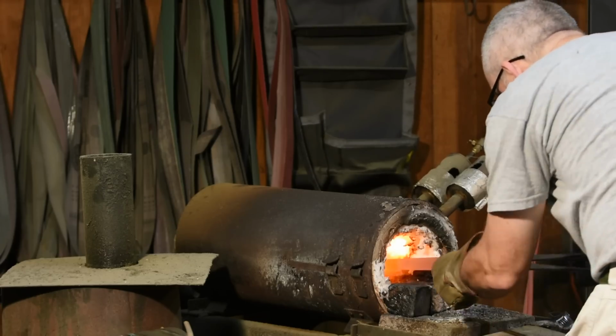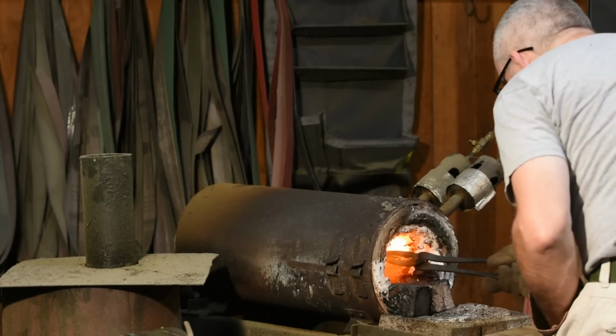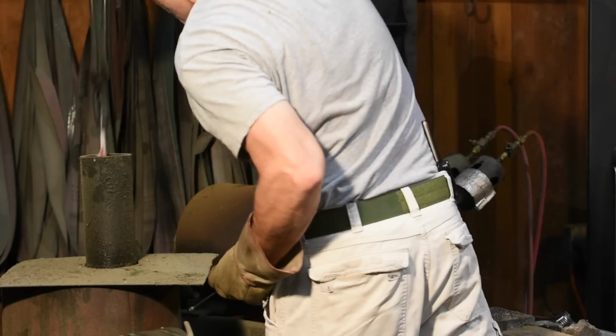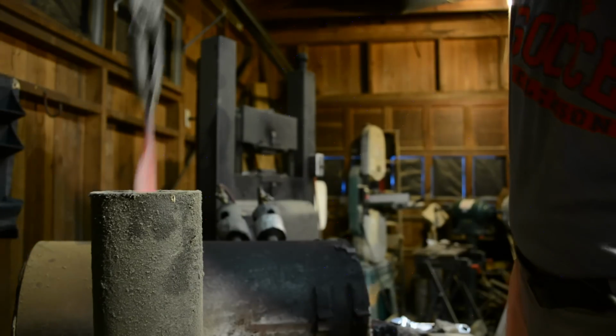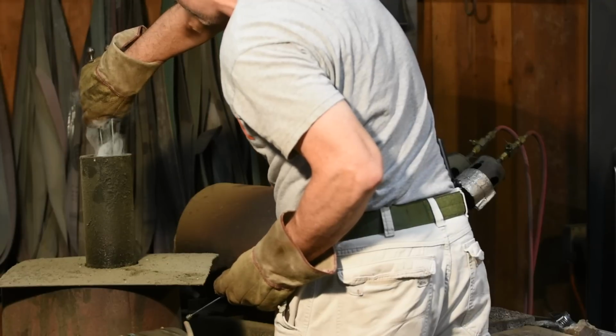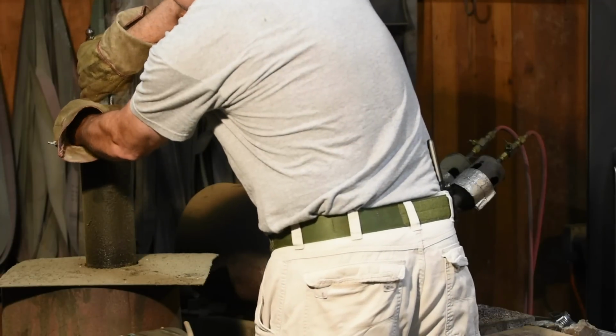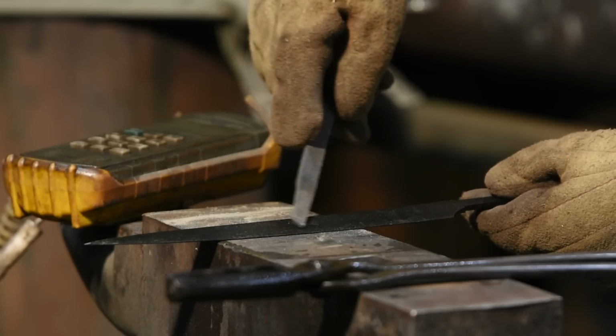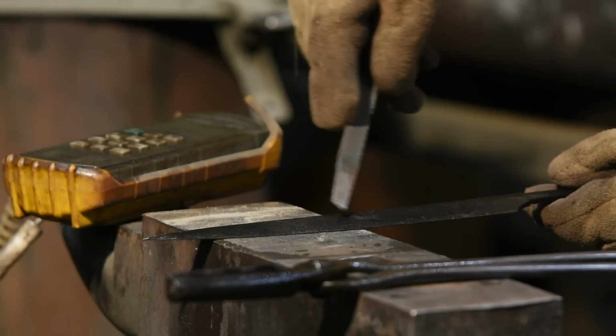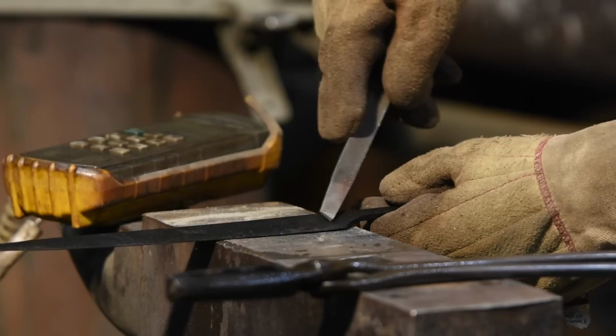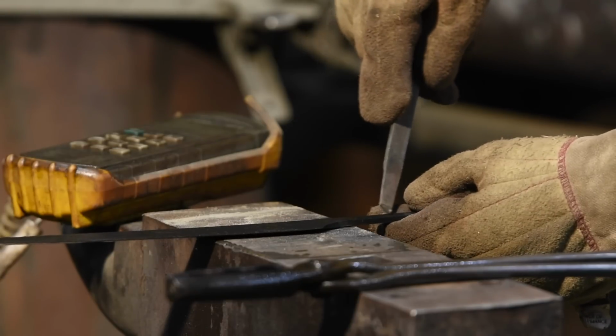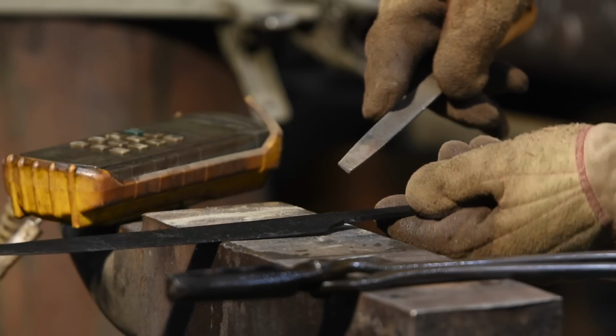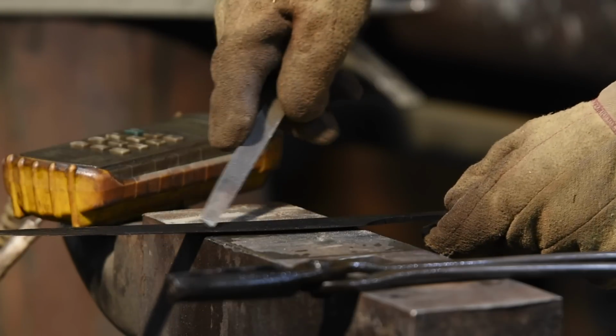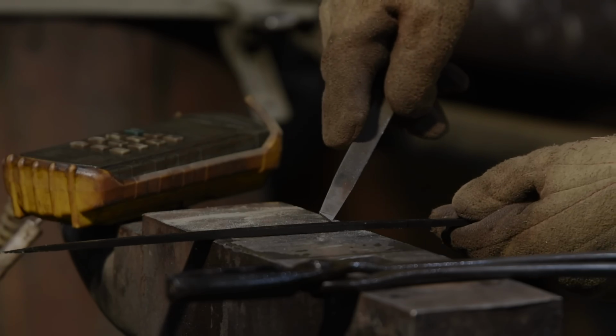When it reaches the right temperature, I'll plunge it into a tube full of warm peanut oil. This will convert the austenite to martensite, hardening the blade. A quick file test indicates that it's hardened. Now, of course, the wrought iron is not capable of hardening, so only the blue steel will harden. Then into the tempering oven at 375 for an hour.